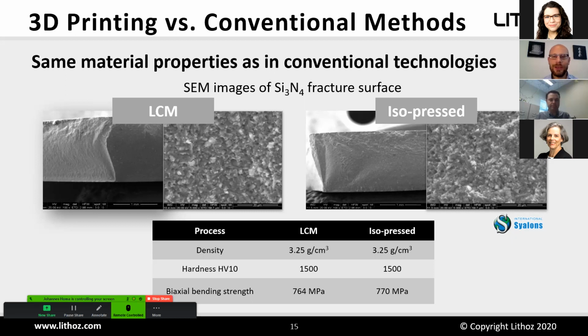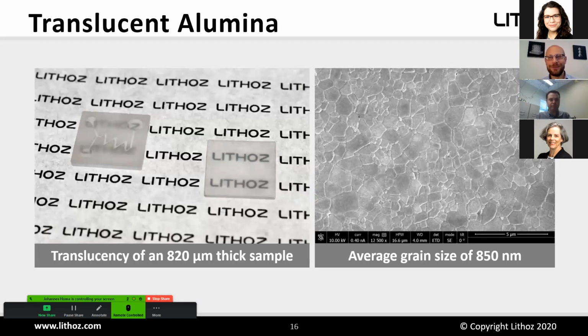Additionally, just to show off a little bit what's really possible with additive manufacturing, and that you see on the level where the technology already is, we can really make transparent alumina. So we have alumina samples, which we of course HIP, and we can get them really translucent so that you can read through a 1 millimeter thick sample. And you see also from the grain structure, grain size, that this is very well controlled. And once you have something transparent or translucent, you cannot hide anything. So this is where you see what's going well and what's not going well.